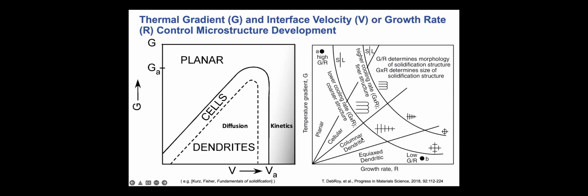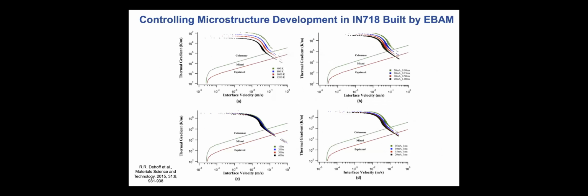So what we mean by that, columnar dendritic means we form these elongated, finger-like grains in the microstructure that can have anisotropic properties, as compared to equiaxed dendritic, more refined microstructures that might have more isotropic properties. And really this G over R, as we've been talking about, determines the morphology of the solidification structure, whereas the G times R, these two curves shown here, actually determine the length scale of the solidification structure. And again, we care about that from a properties point of view. So how does this apply to additive manufacturing?